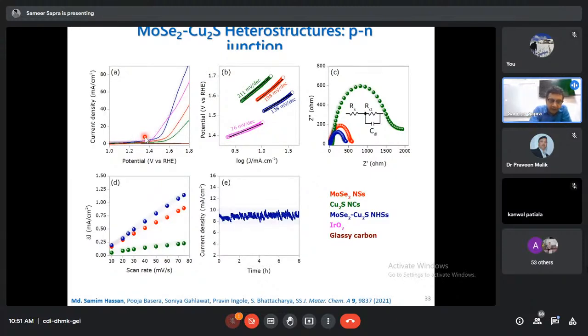And if you look at this curve, the pink purple curve, that is for iridium oxide, which is the standard for oxygen evolution reaction. If you look at the blue curve, that is molybdenum selenide cuprous sulfide, although it has a slightly higher overpotential, if you go to about 1.6 volts, you'll see that it gives much higher activity than iridium oxide too.